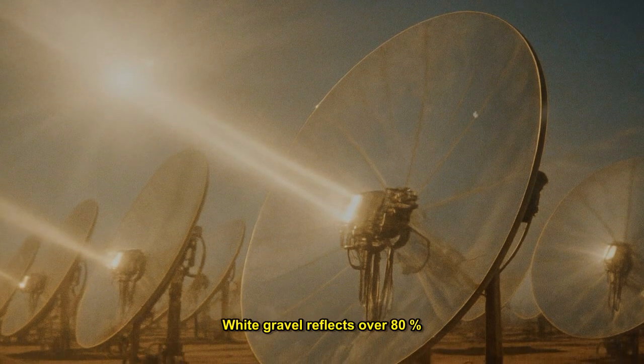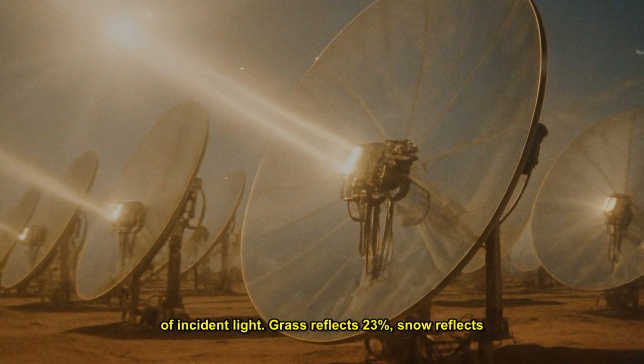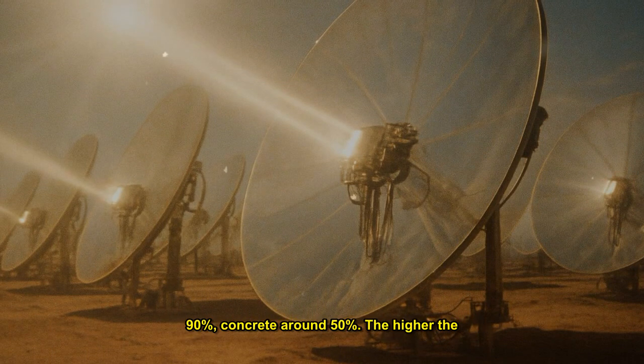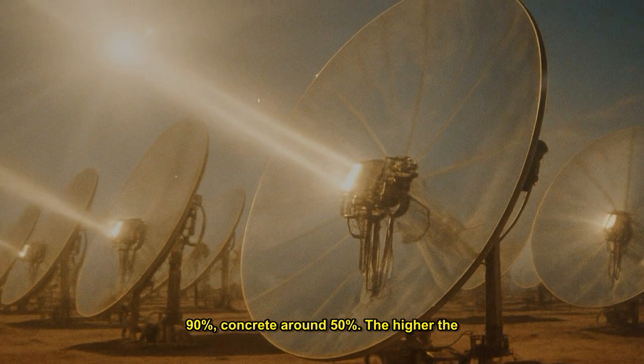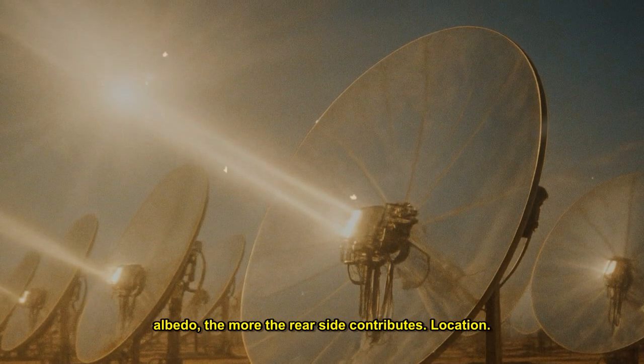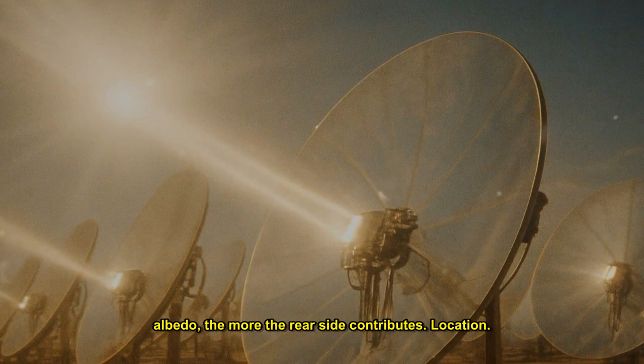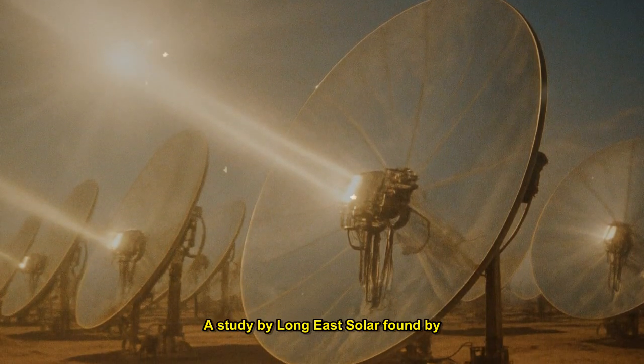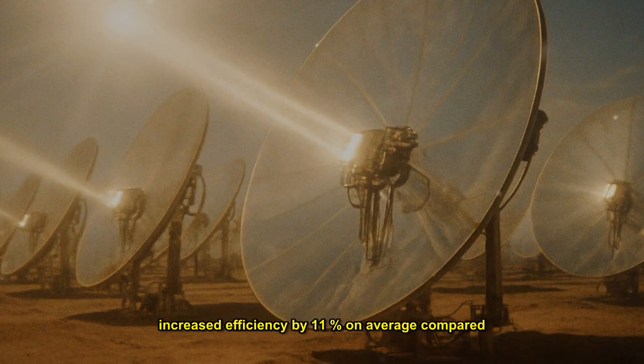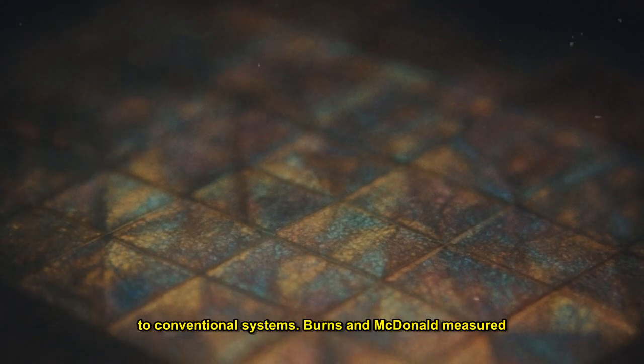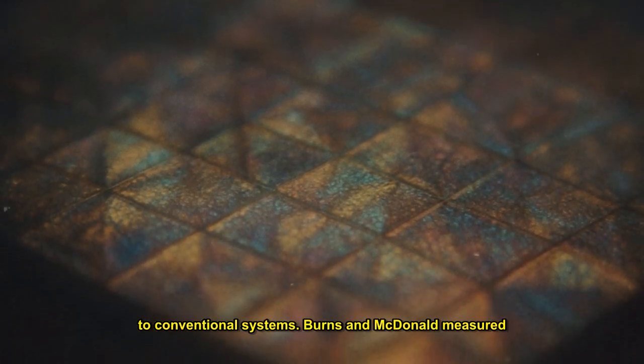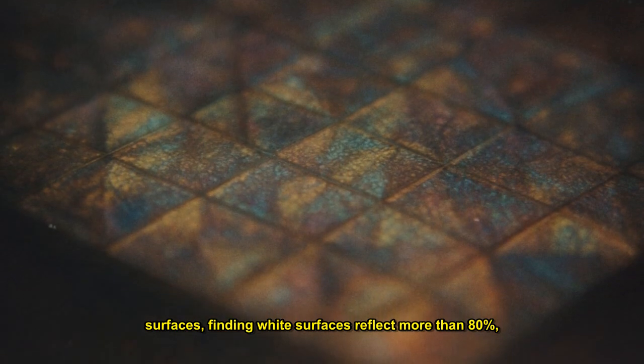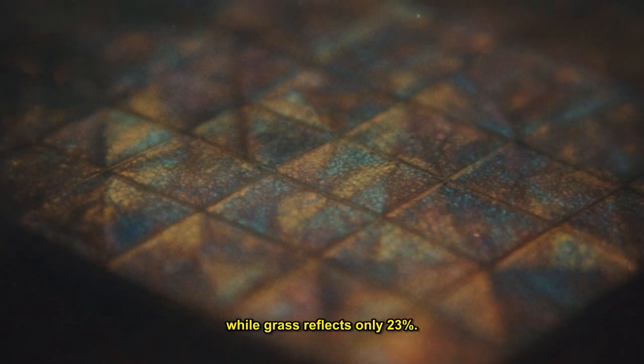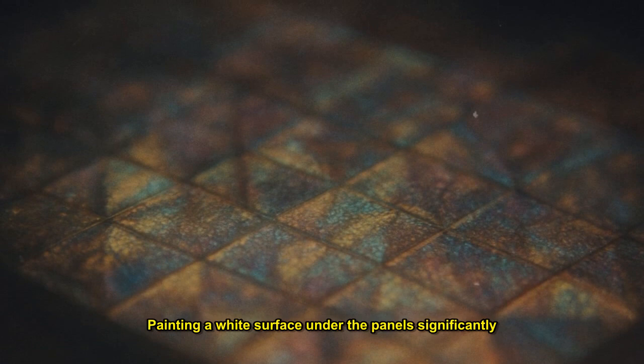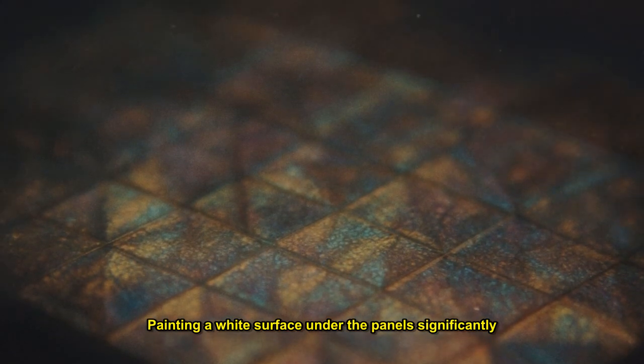White gravel reflects over 80% of incident light. Grass reflects 23%. Snow reflects 90%. Concrete around 50%. The higher the albedo, the more the rear side contributes. Location. A study by Longi Solar found bifacials increased efficiency by 11% on average compared to conventional systems. Burns and McDonnell measured surfaces, finding white surfaces reflect more than 80%, while grass reflects only 23%. Painting a white surface under the panels significantly boosts rear side generation.